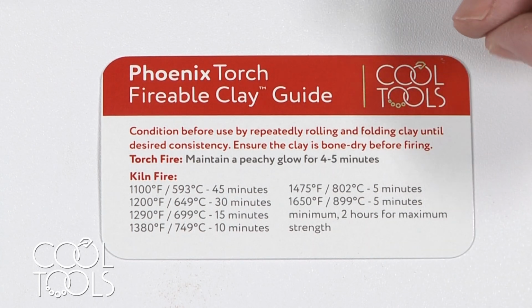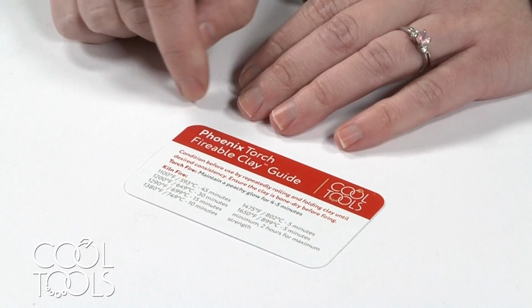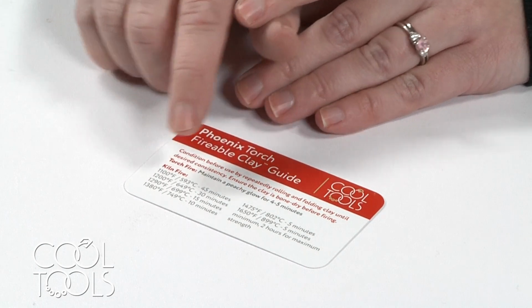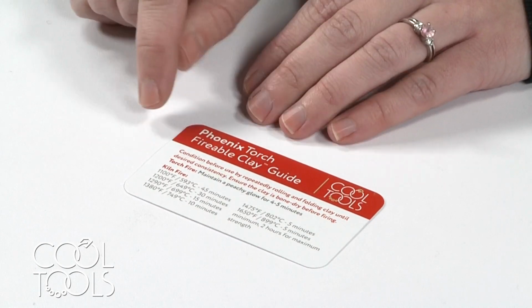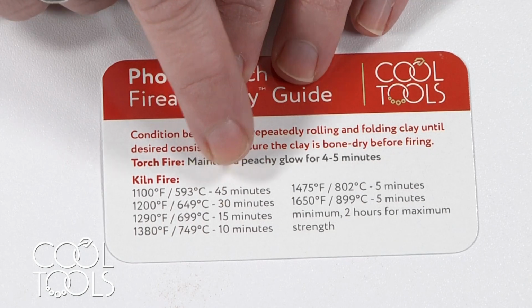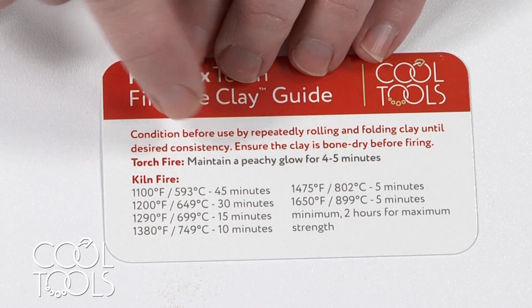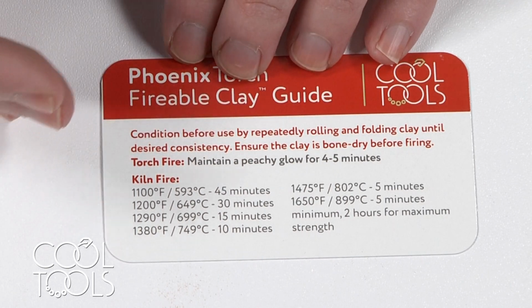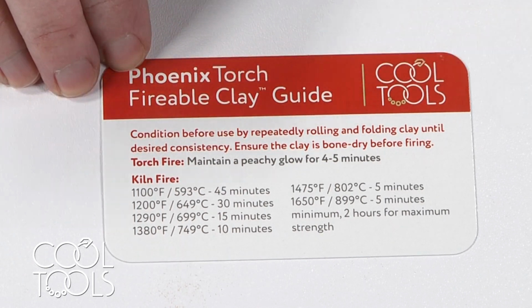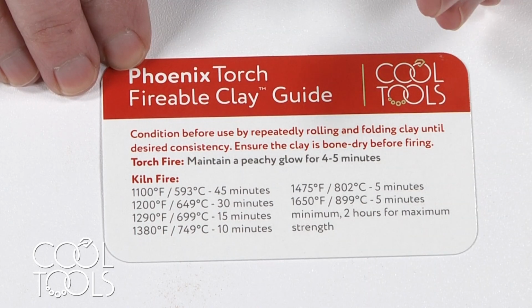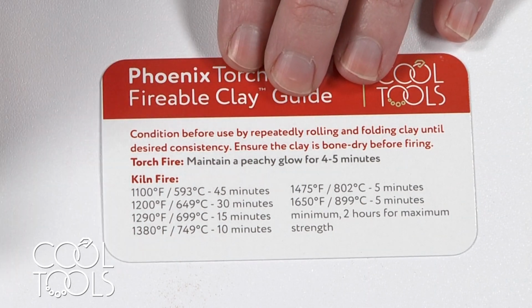for maximum strength. Just to clear up any confusion that you may have with these firing schedules, this is a minimum temp and a minimum time. You can fire at 1,100 degrees for longer than 45 minutes if you would like, but it must be fired at a minimum of 45 minutes. You're never going to fire your clay for too long at a certain temperature. You can take it too hot and experience melting, but you're never going to fire your clay for too long.